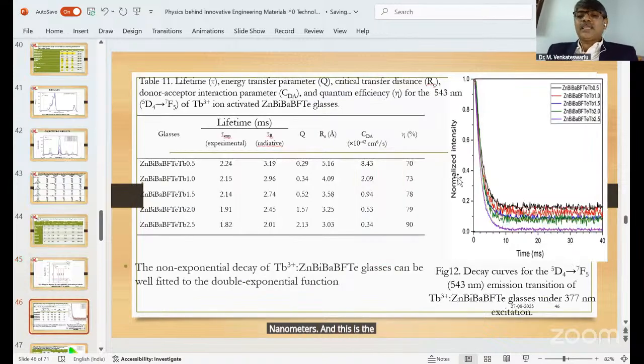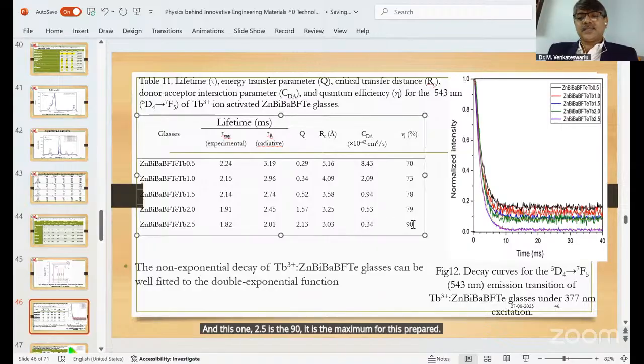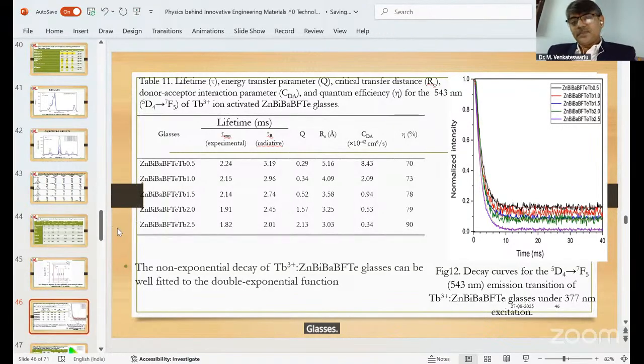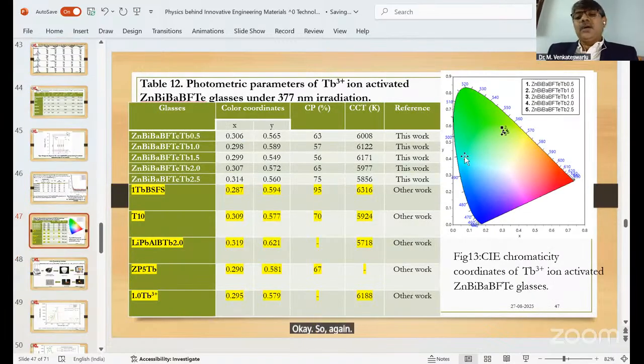And this is the exponential decay of the terbium doped glasses. For this, we have calculated the tau experimental, tau R, and quality factor. Then we have the quantum efficiency. The 1 mole percent sample has a high quantum efficiency of 73%, and the 2.5 sample is 90%, which is the maximum for these prepared glasses. Again we have drawn the CIE chromaticity diagram. In this you can observe that it lies in the green region.